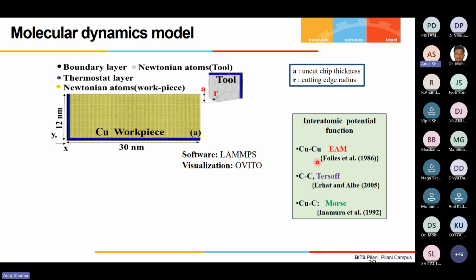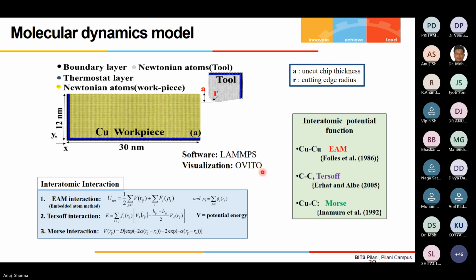Their interaction can be easily analyzed with the help of the Tersoff potential. So there we need to model it with the Tersoff potential. And between the copper and carbon, because the tool is carbon and the workpiece has copper atoms, the Morse potential is used. That is a very good potential to study the surface interaction between the tool and workpiece. Here A is the uncut chip thickness and R is the tool edge radius, the cutting edge radius. The software I used for simulation was LAMMPS, and for visualization there was the OVITO software. These are the formulations of the different potential functions: the EAM potential function, the Tersoff, and the Morse.